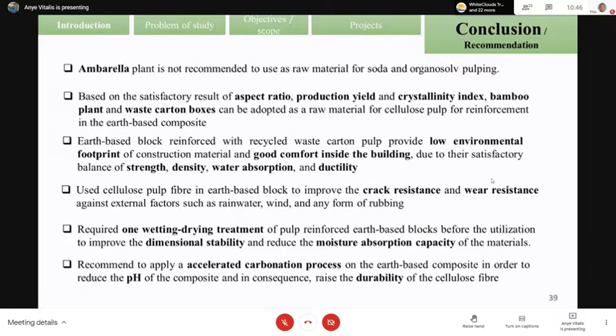Also, earth-based block reinforcement with recycled waste carton pulp provides low environmental footprint and energy consumption and good comfort inside the building due to the satisfactory balance of strength, density, water absorption, and ductility. Also, by using this cellulose fiber, you can improve the crack resistance and the wear resistance against external factors in our earth-based material. It requires using one cycle of wetting and drying treatment, which will help to have a good dimensional stabilization and reduce the moisture absorption capacity of our material.